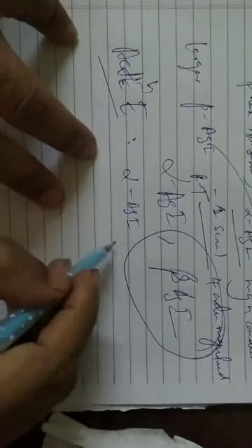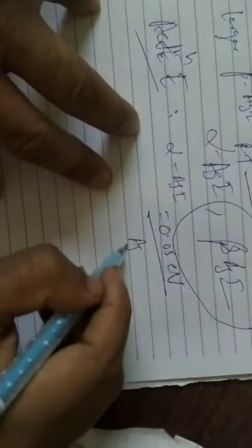Even the activation energy for conduction in alpha AgI is very small, almost 0.05 electron volt, and the structure is suited for easy motion of Ag plus. That's why I mentioned this structure.